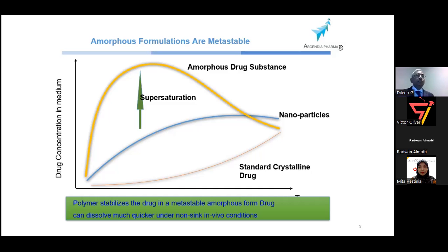So in these polymeric dispersions, the drug is fully converted to the amorphous state, the meta-stable state, and of course it can stay there. But then how can you stabilize those molecules in the meta-stable state in a polymer, right? That's really challenging. And how can you maintain the stability for the next 2 or 3 years in the tablet form? So you're developing tablets or capsules, how can you do that, right? With nano dispersion, nano solutions, and nano suspension, we can still increase solubility, not to the extent we like, so we further enhance the solubility by amorphous dispersion.